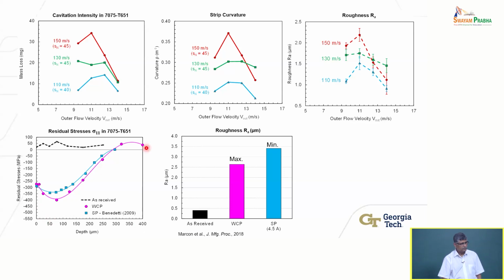Okay? Yes? So this sigma 11 is the periodic component of the stress? This is basically the stress component in the direction of, in this case, a surface that was actually peened, right? So this is the in-plane stress component. These are elastic stresses. Deviatoric stresses would essentially be what generated the plastic deformation. So actually any process leads to the plastic. Correct, correct. But what we are measuring is after you removed all loads. So what is remaining in the material is elastic stresses. And sigma 11 is the x direction principal stress component.